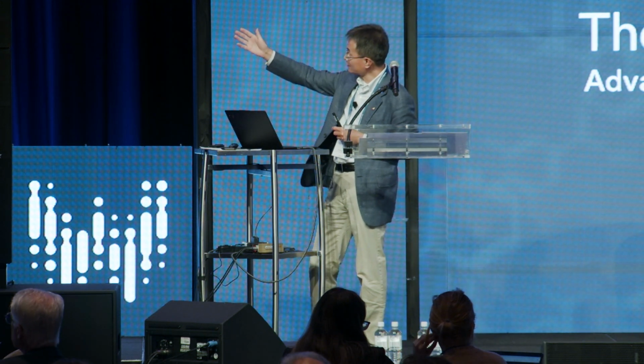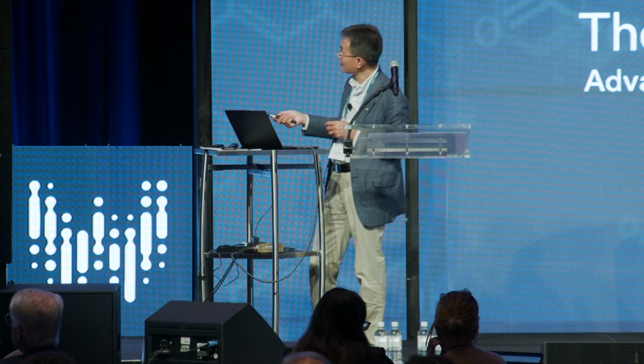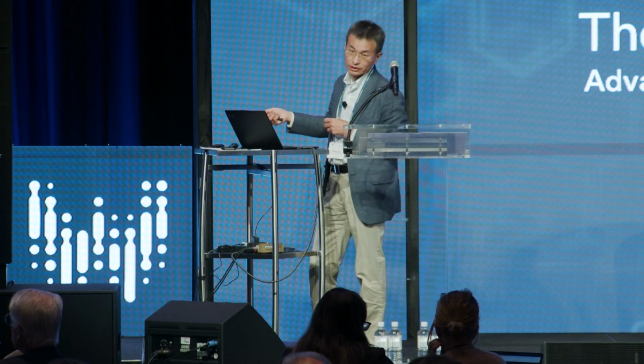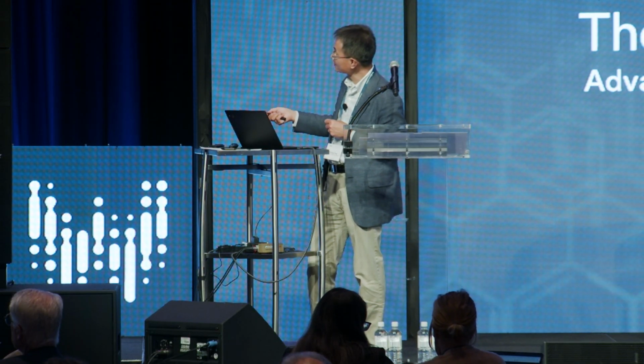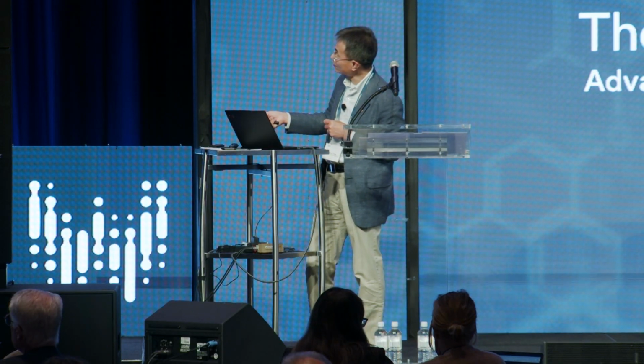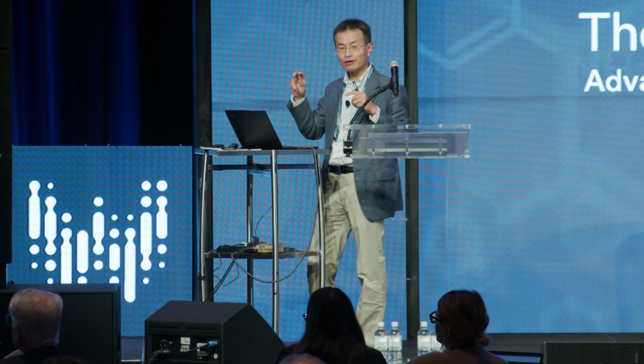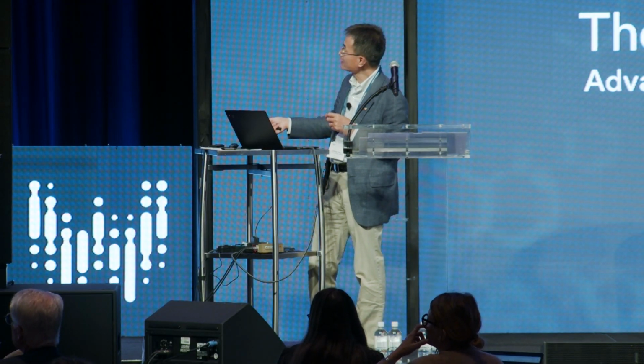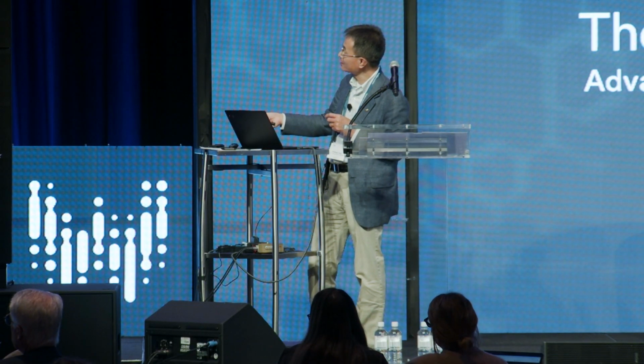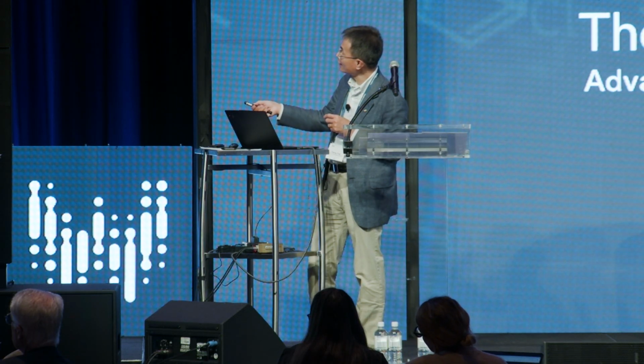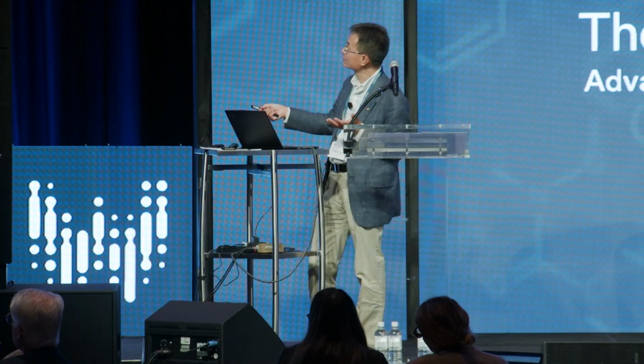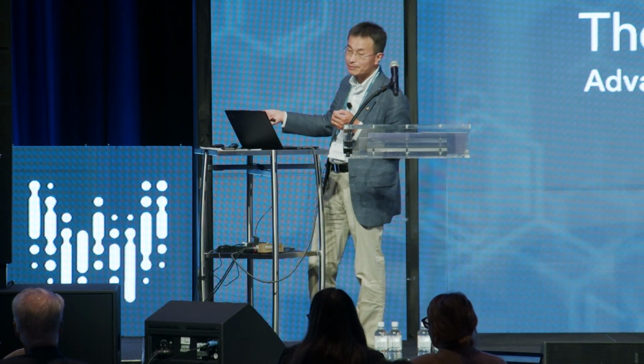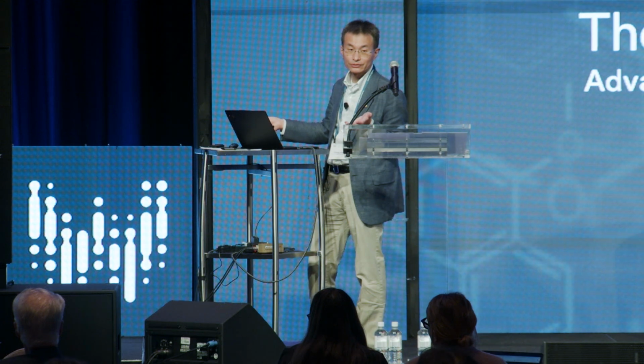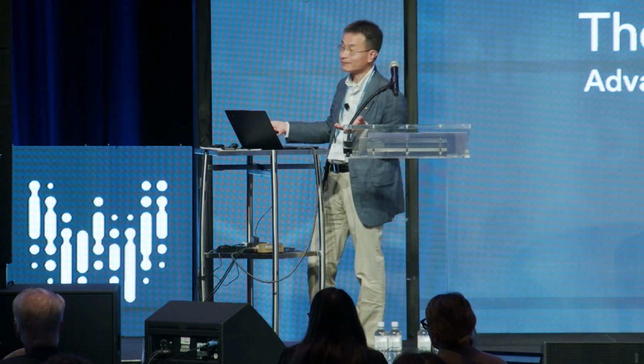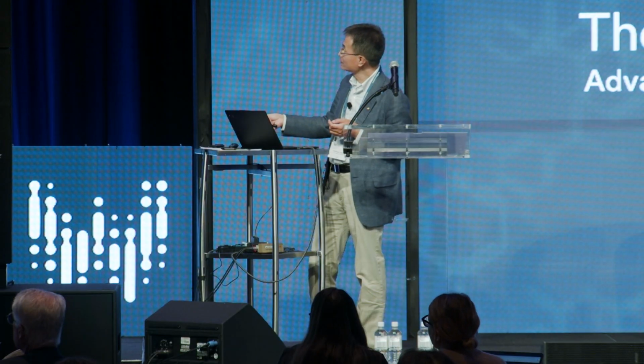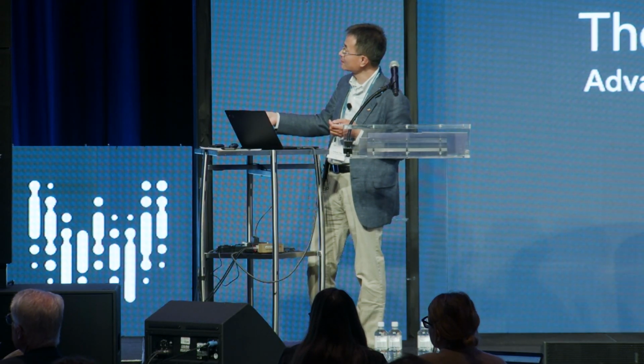Now, if you put together these nanowire photochemical diodes, you can run water splitting by combining p-type and n-type semiconductors. This so-called cross point is the bias-free operating current density. We can do it typically at sub 5 milliamps per square centimeter to generate oxygen and hydrogen. In this case, the photovoltage supplies the thermodynamic voltage you need for water splitting, the 1.23 eV, plus all the overpotentials. That's durable.